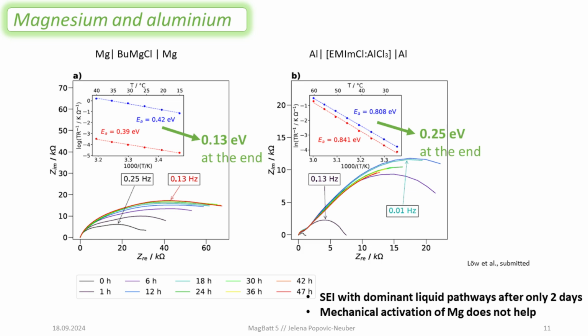What I can tell you is that if we look at the activation energies, we see at the beginning that it's around 0.4. So we are, again, somewhere in between the liquid and the solid state. So it's not very liquid, it's not very solid, it's really in the middle. But with time, at the end, here the end is something around 47 hours, we see that this activation energy gets lower.